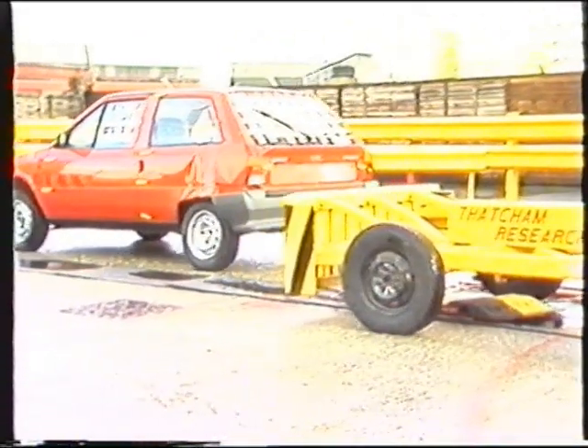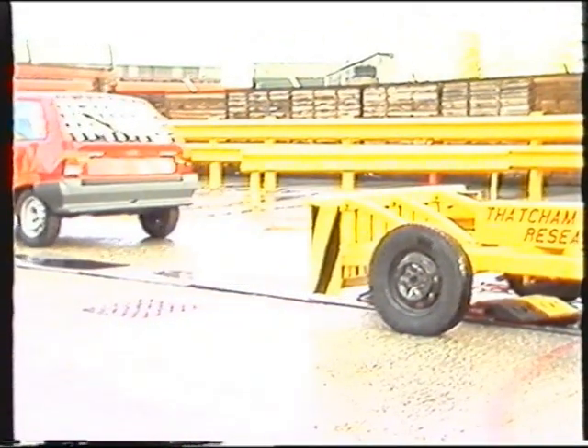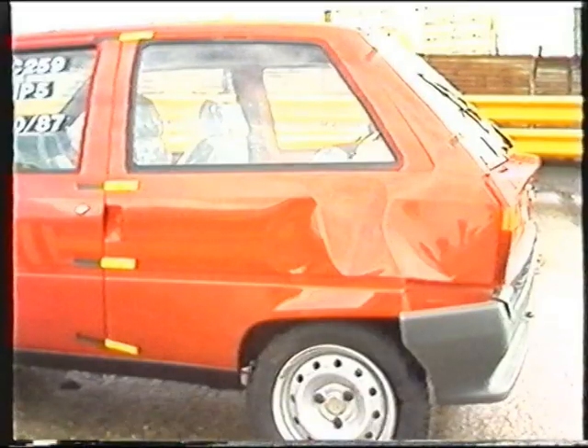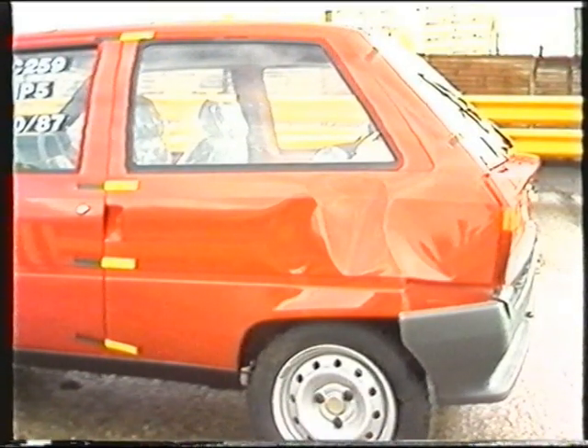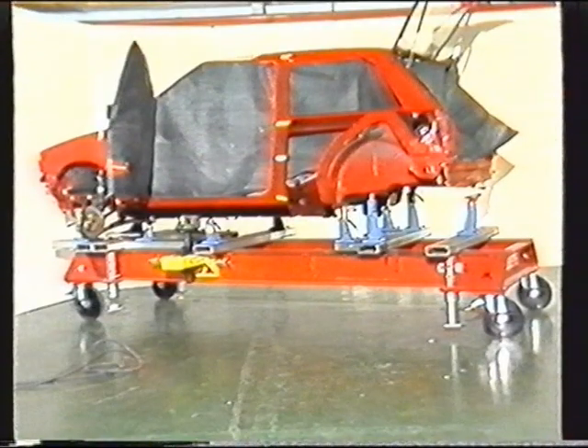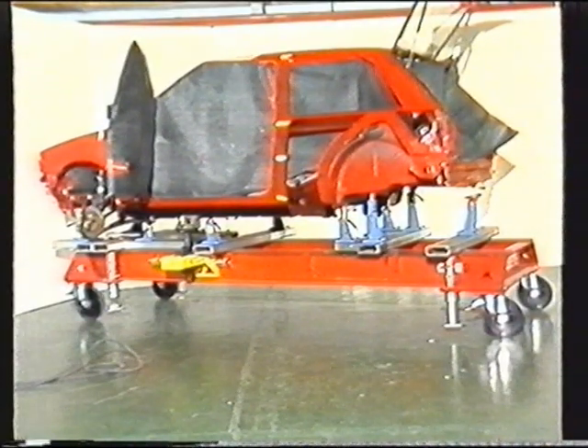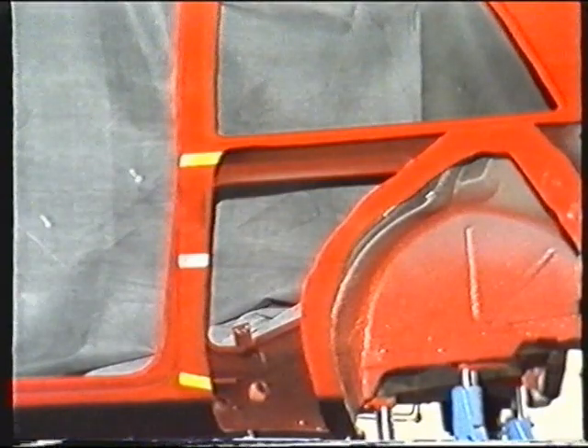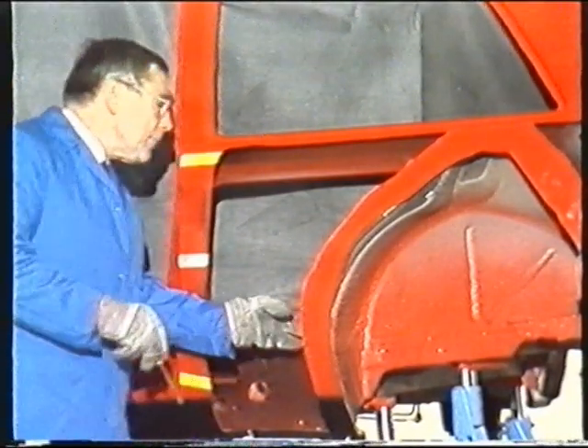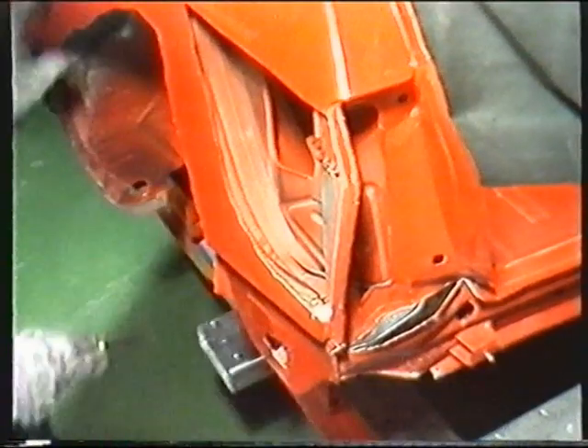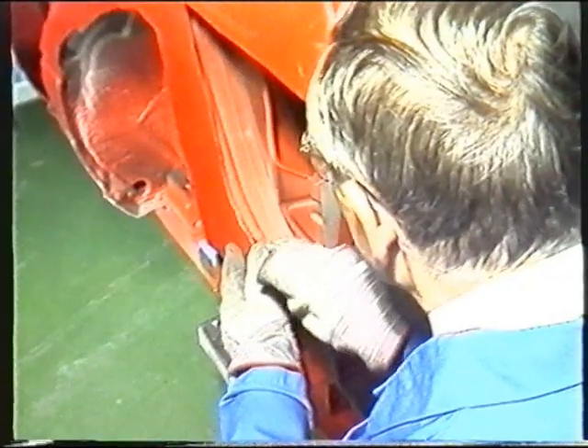The wheel arch on this Citroën AX has been damaged by the impact. Because it was bonded in manufacture, an adhesive can and will be used in the repair. The bulk of the panel was cut away so that a check could be made on the condition of the bonded joint after impact. Investigations revealed that the bonding material was not a true adhesive, but an expanding foam PVC, which required a curing temperature of about 120 degrees centigrade to activate it. Such a temperature would cause damage to a finished vehicle.